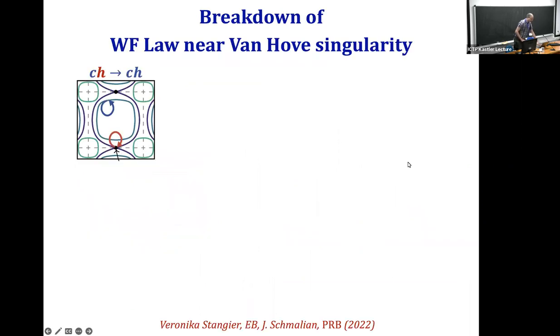Okay, so coming back to the example of a metal tuned close to a Van Hove singularity. So what's expected to happen there? We saw that there are these CH to CH scattering processes that involve a very small momentum transfer and don't show up in the electrical resistivity, but these are inelastic scattering. Okay, so they can relax the quasi-particle energy, and therefore we expect them to show up very strongly in the thermal resistivity. Okay, and this might lead to a very strong violation of the Wiedemann-Franz law.